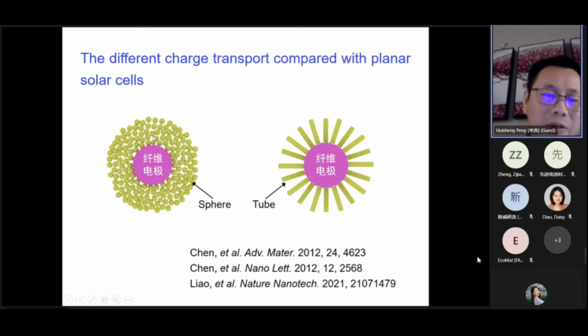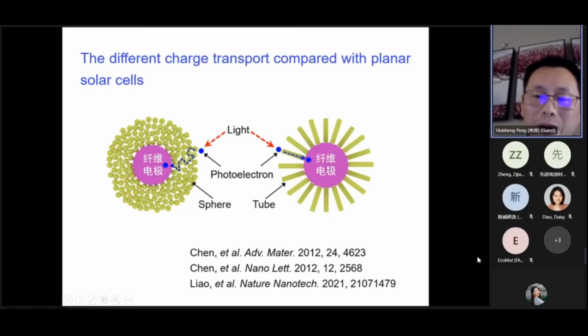For example, for the active materials on the fiber electrode, if they are spheres, the photoelectrons will transport through a long pathway. For nanotubes or nanorods, it can be a very short path length. And more importantly, these nanotubes or nanorods go in the radial direction, and as the space increases, the dye molecules can go through and reach the bottom. So for the whole electrode, it can be very efficient. If it's planar, it's very difficult for the dye molecules to go inside.